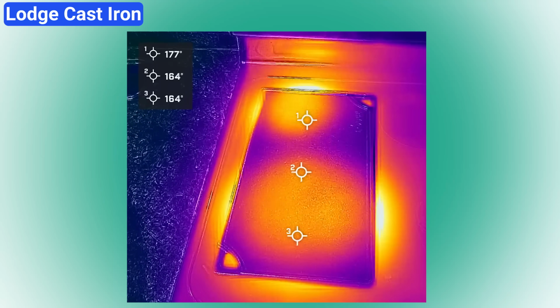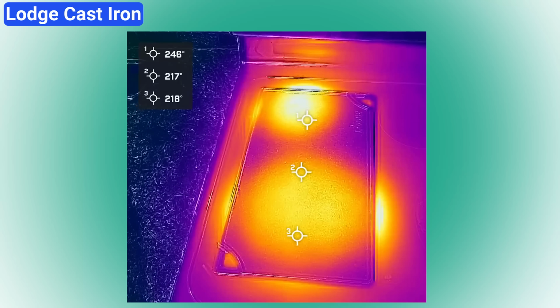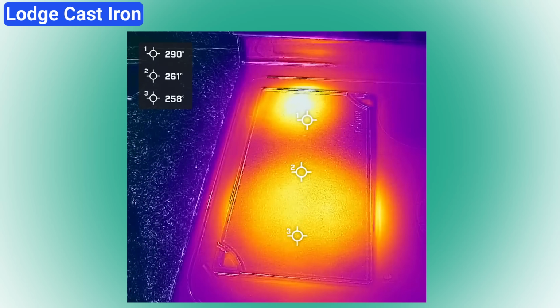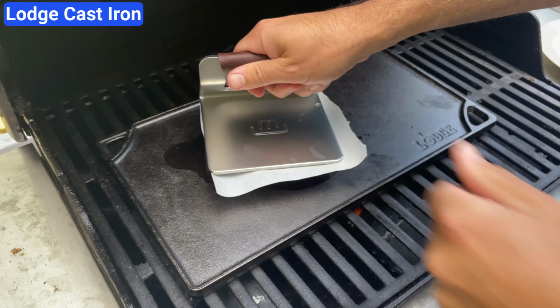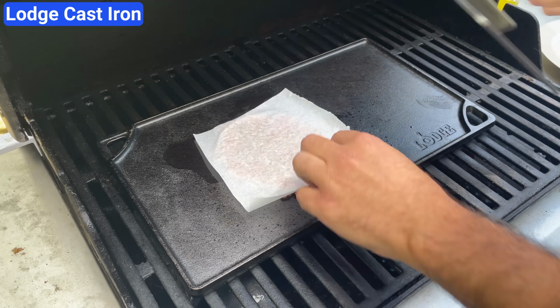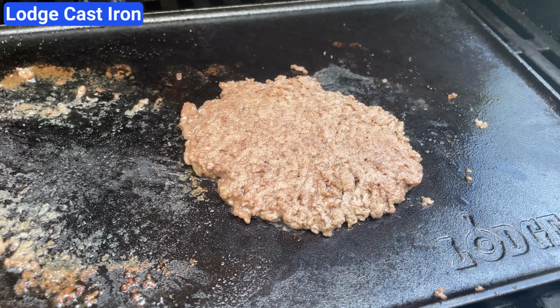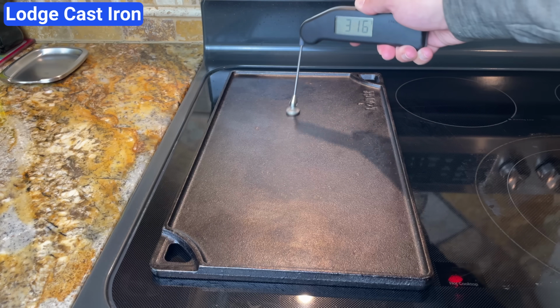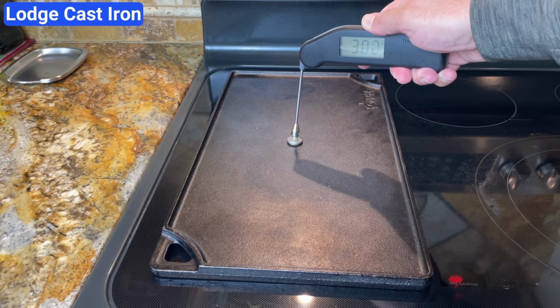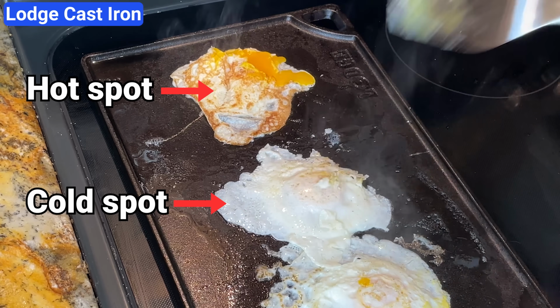On the negative side, it's by far the slowest griddle to heat, and it takes a long time to get hot enough for searing. My first attempt at smash burgers failed because I didn't preheat it long enough. The meat cooked through before the crust could form. It also reacts slowly when you adjust the burner, and cold spots where the griddle isn't directly over the heat